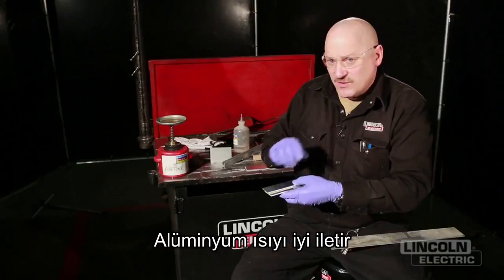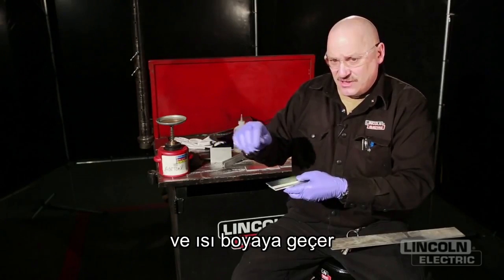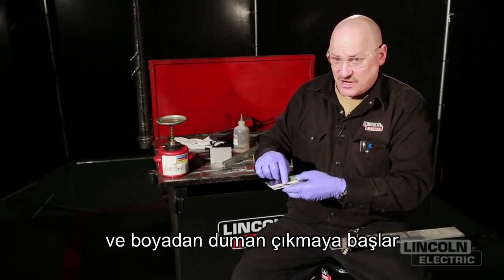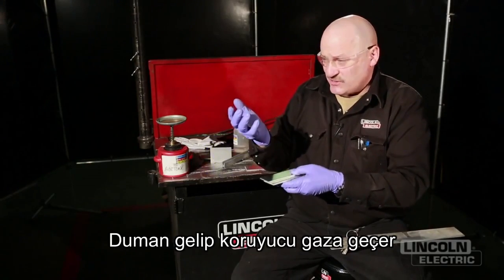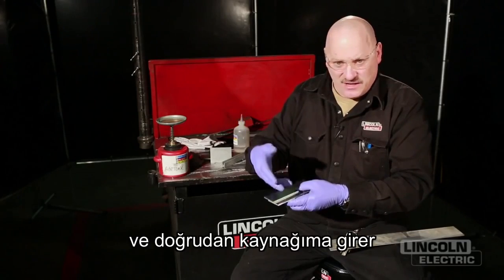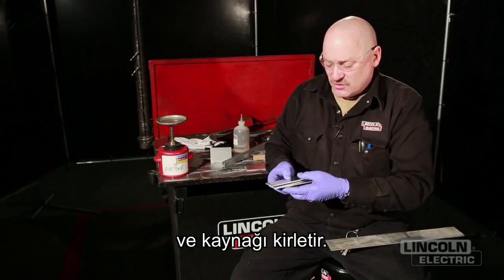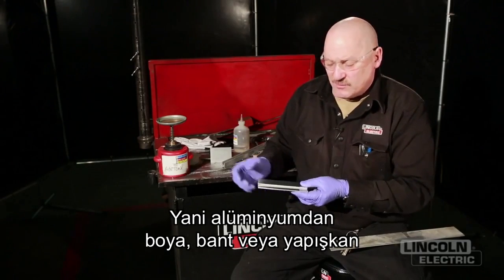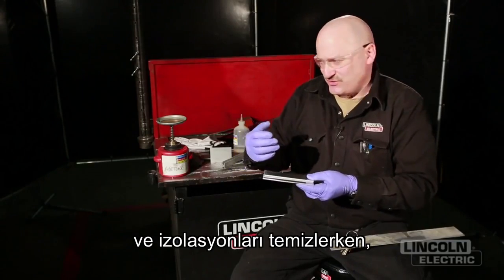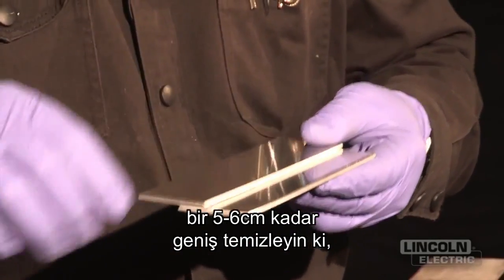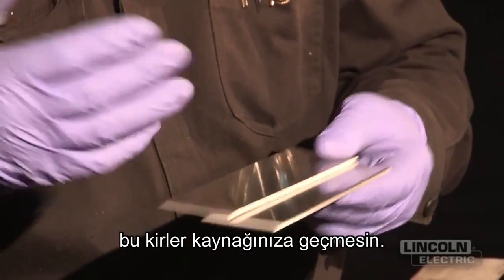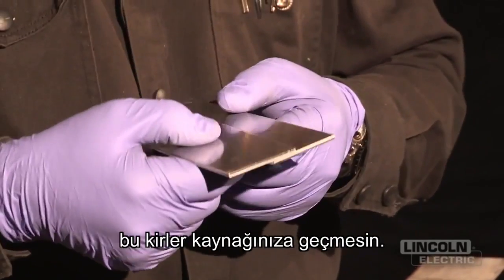Well, aluminum conducts heat real fast, and the heat gets into that paint, and what happens is the paint starts to smoke. The smoke comes up into my shielding gas, and it goes right down into my weld, contaminates the weld. So really, when you're going to clean paint off of aluminum or tape or glues or sealers, you got to clean back a couple inches. Clean back a ways so that the contaminants don't come up into your weld.